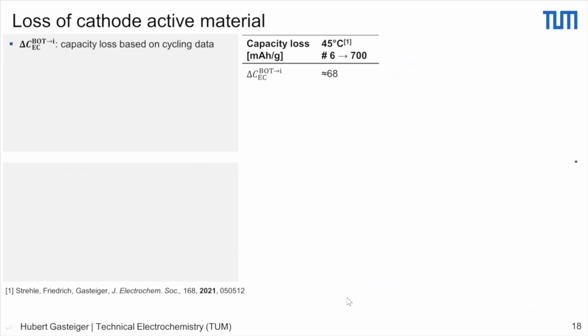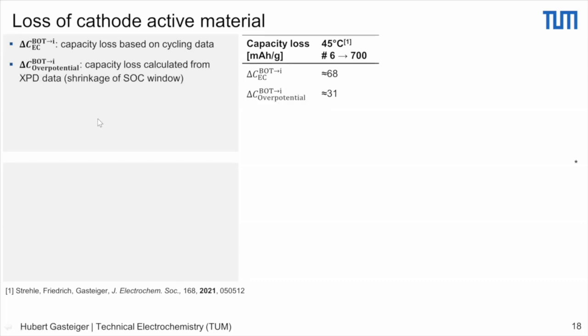Okay, so now, last slide. What is the active material loss? How can we actually determine it? And so we can look, what is our capacity loss from beginning of test until a given cycle? So from cycle 6 in this case to 700 cycles, we lose about 68 mAh/g. Now we can calculate how much we would lose because of the shrinkage of the SOC window, which is due to polarization due to overpotentials. That is calculated from the XRD data shown before, and there we would lose about 31 of these 68 mAh/g.